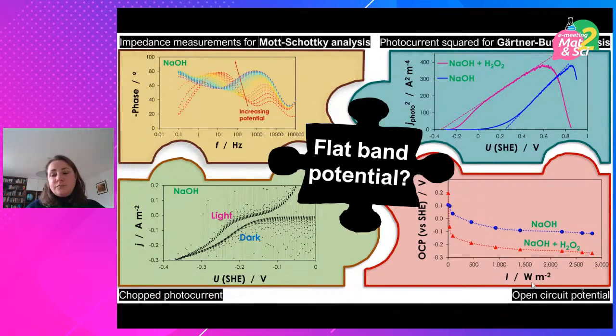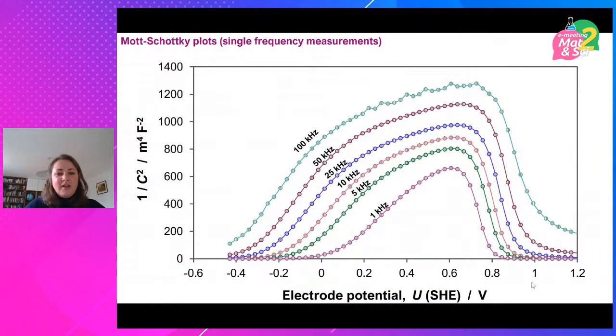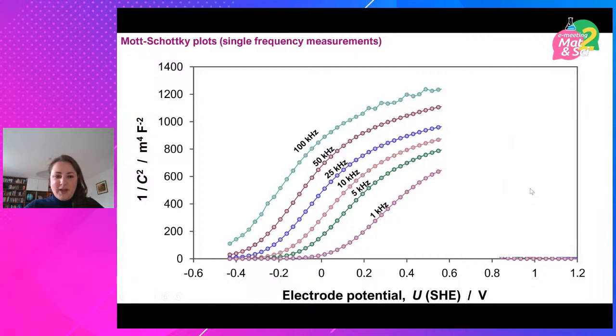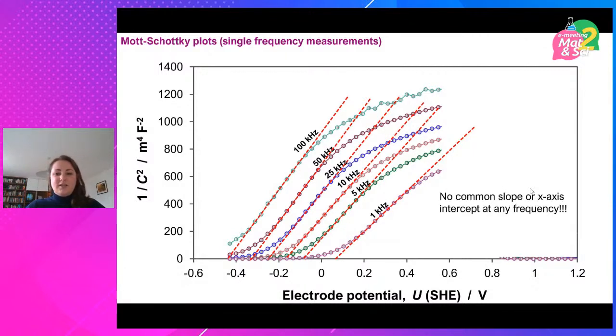And of course, this procedure wanted you to select a frequency of the perturbation at which you wanted to plot the Mott-Schottky graph that you can then extrapolate to find your flat band potential. So we tried several frequencies, and this is what we got. By the way, not everybody gets such a huge dispersion, but we looked at this and thought, well, where's the flat band potential? Okay, you have some kind of p-type behavior where oxygen evolution occurs, so let's just ignore that and focus on the n-type behavior. And then we put lines of best fit through all of these curves and didn't arrive at a single value of doping density or at a single intercept.